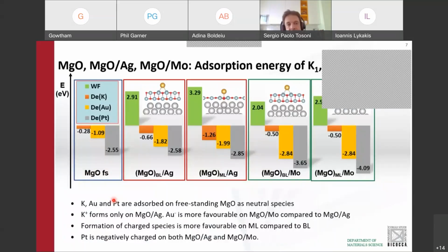So let me start by examining the main results on MgO. As I said, we are considering the adsorption of three types of atoms: potassium, gold, and platinum. And in these histograms, I'm reporting the adsorption energy of these species on MgO. And in the case of metal-supported MgO, I'm also reporting with the green histogram the work function of the system.